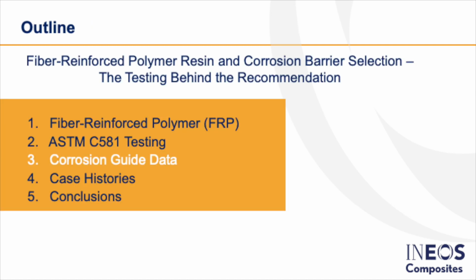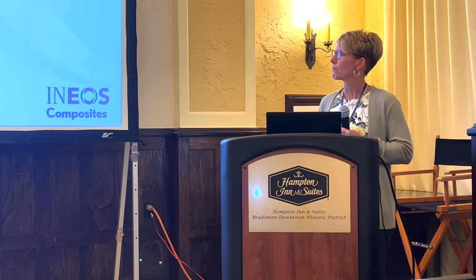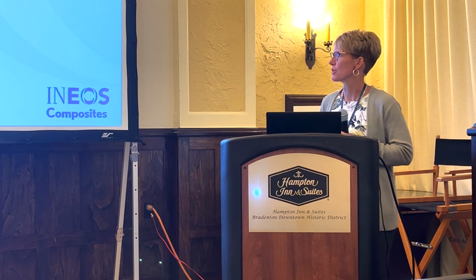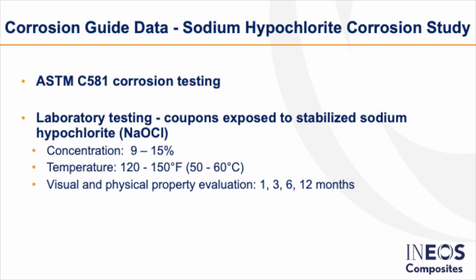Now I'll go through an actual study that we did and how we gathered that data and then use that to make different recommendations. So in this study, again, we did it according to the ASTM C581 standard. We tested 9 to 15% sodium hypochlorite, temperatures between 120 and 150 degrees Fahrenheit, and then did the visual and physical property evaluations at 1, 3, 6, and 12 months.